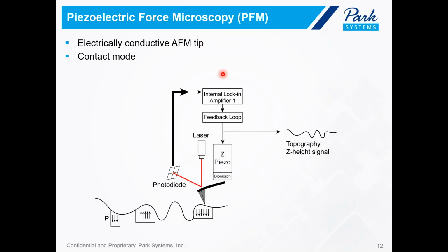The schematic here shows how a topography signal is generated in contact mode, basically. We have a laser that hits the back of the cantilever and is reflected by the back of the cantilever and directed to a position-sensitive photodiode detector, or the photodiode here. The AFM tip is raster scanned across the sample, and changes in the sample topography produce changes in the laser position on the photodiode. And this signal will pass to a lock-in amplifier and through a feedback loop, and eventually to our Z piezo to keep the force at the tip-sample contact point constant. So this is how we would get the topography signal in contact mode.